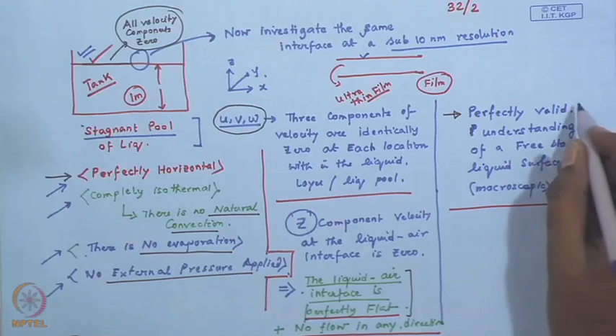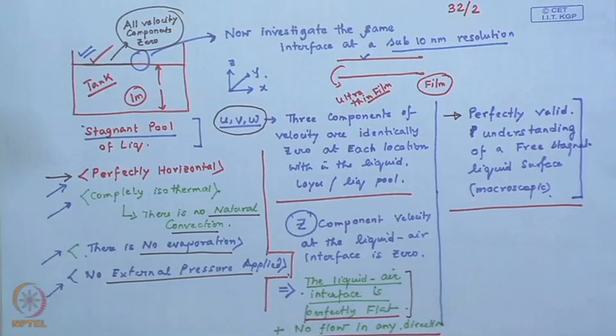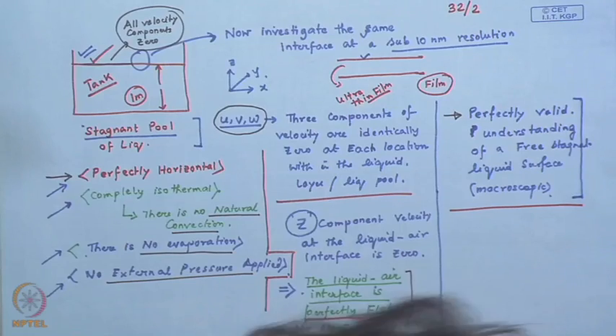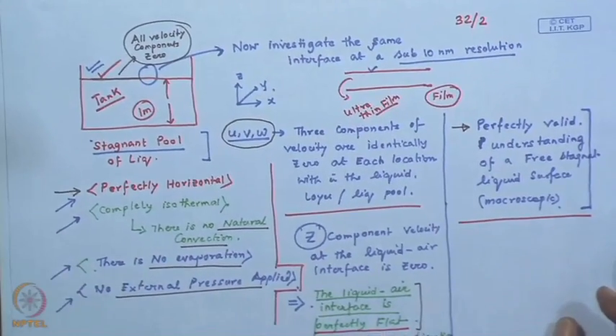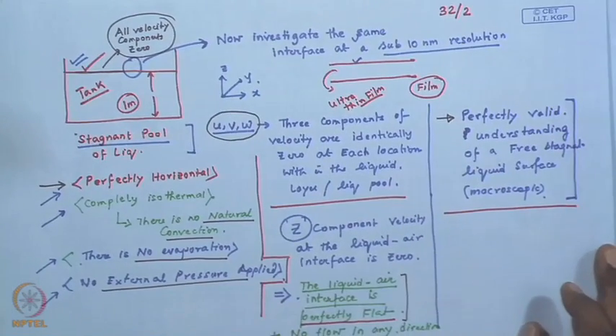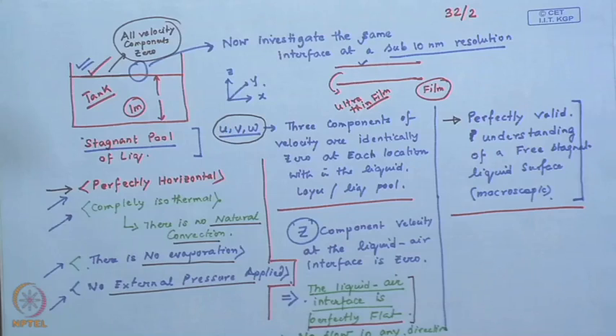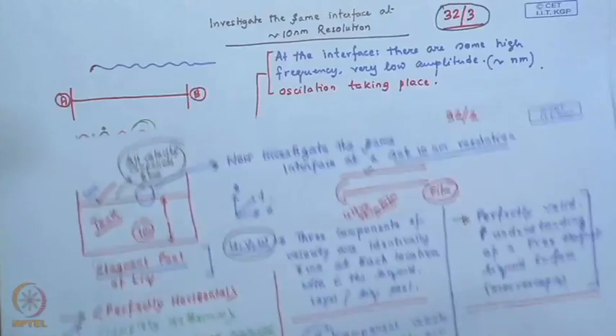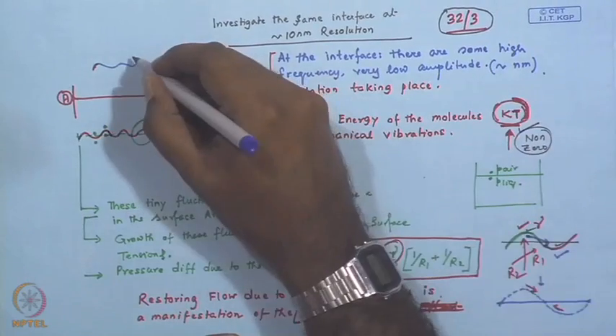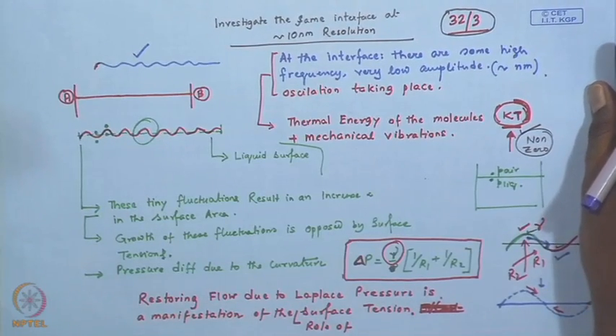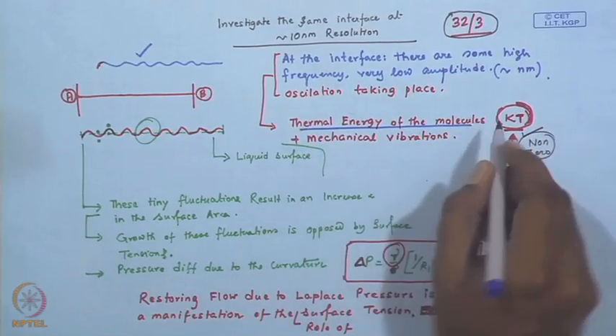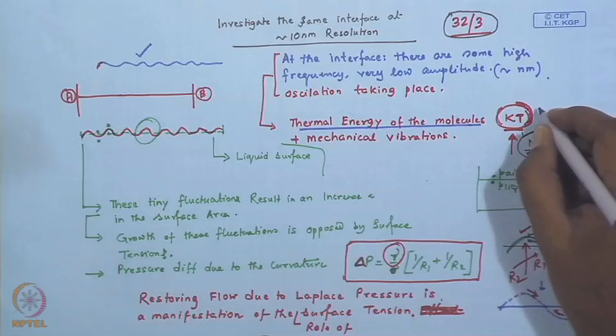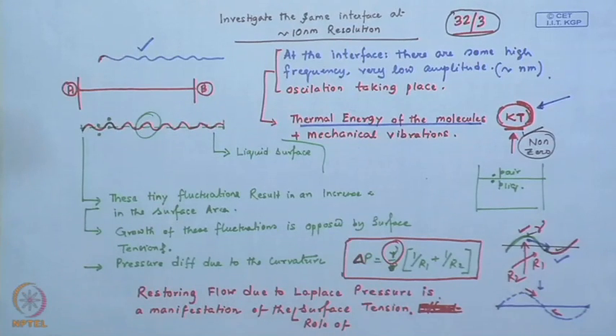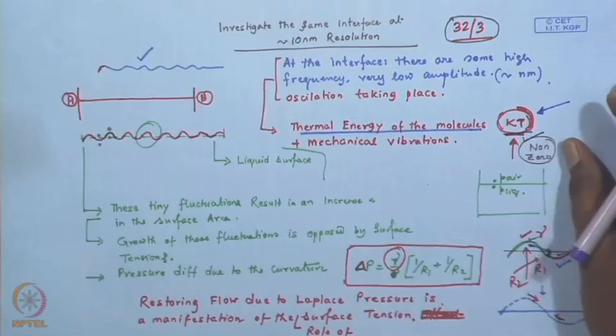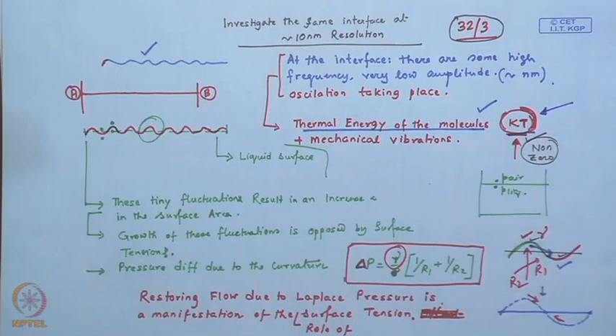We argued that this is a perfectly valid picture of the interface if you are talking about macroscopic length scale, but when we investigate the same interface at a sub 10 nanometer resolution, let us say, we find that there are some very tiny fluctuations present on the surface of the liquid, the origin of which is attributed to the thermal energy of the molecules, which is omnipresent because it scales as kT. If you are operating at a temperature which is not absolute 0, then this component of energy you can never eliminate, and you can also have some mechanical vibrations.